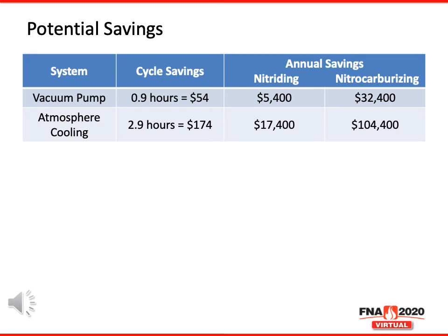So if we look at the vacuum pump with these cycle parameters, there was just under an hour's worth of savings at $60 an hour. It gave us a $54 savings per cycle. And so if we look at the number of cycles over the course of a given year, you can see on a nitriding cycle about $5,400 worth of savings. On a nitrocarburizing cycle, again, you're running many cycles. There are many opportunities to run that pump and shorten the purge timing, looking at potentially $32,000 in savings.